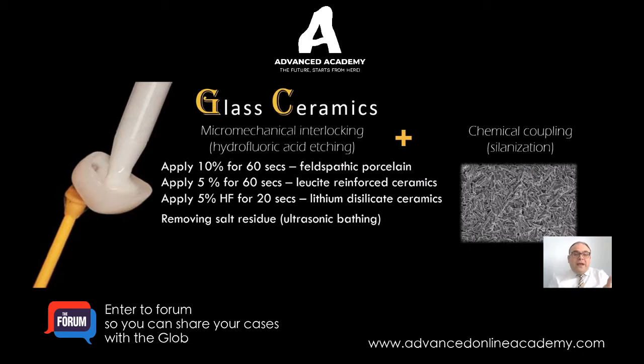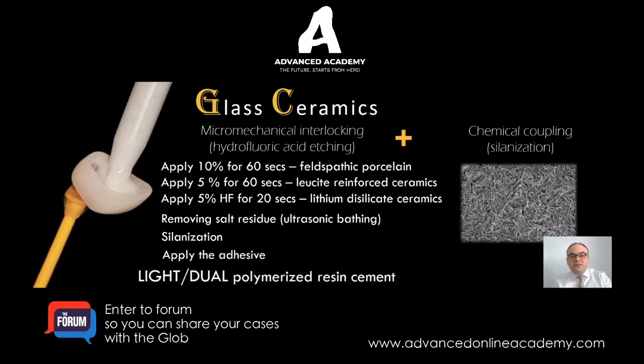If you over etch, you sometimes see an excess chalky white appearance on your ceramic. That means salts have developed due to the higher concentration or longer etching period. Therefore, you need to remove that. Either ultrasonic bathing or light sandblasting will get rid of these salts, so you have a cleaner surface. Then your ceramic primer, your silane or the adhesive, usually now they're combined into one, containing the MDP monomer. With the ceramic material you can use a light or dual cure resin-based cement.